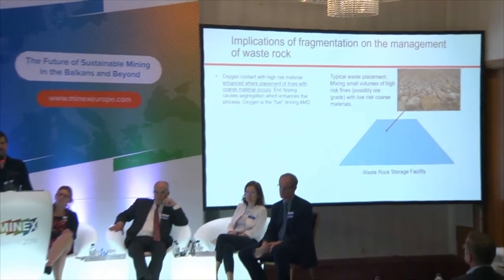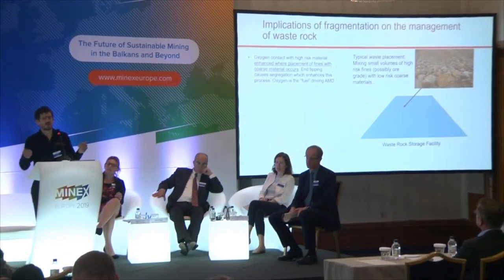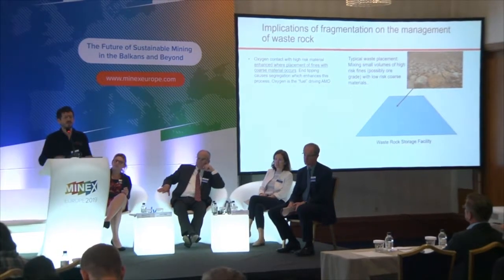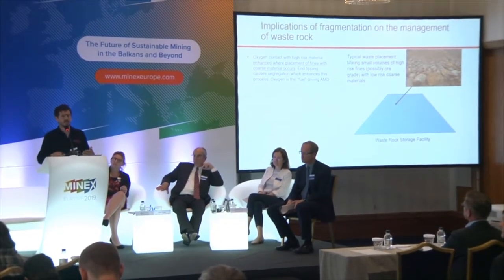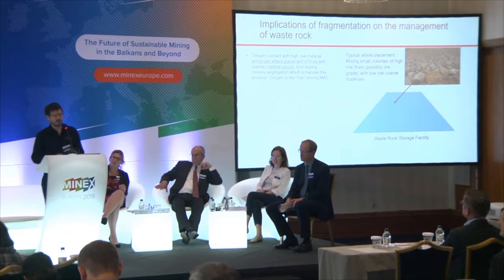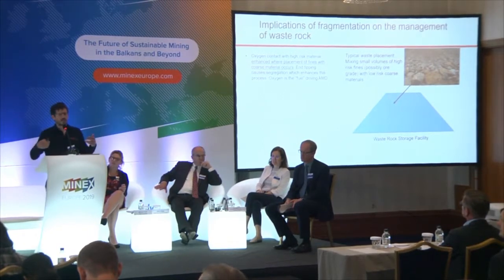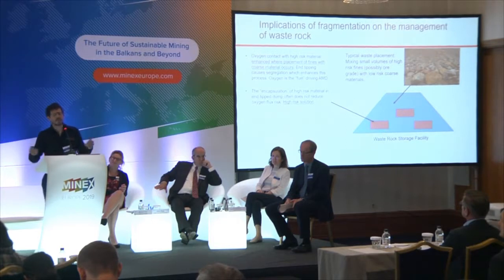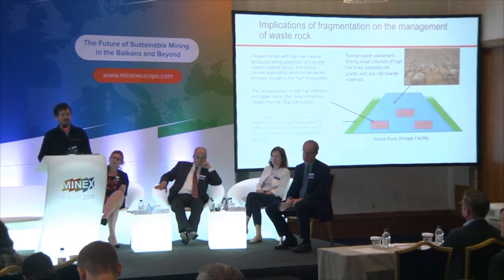And the problem with that is that acid mine drainage comes from reaction of oxygen and sulfides. If you mix in coarse and fines, you're encouraging oxygen to get in. So mixing the two materials together is the worst thing that you can do. Even encapsulating this material doesn't necessarily work, because although it's called encapsulation, you're still mixing coarse and fine, you're still getting air into there.